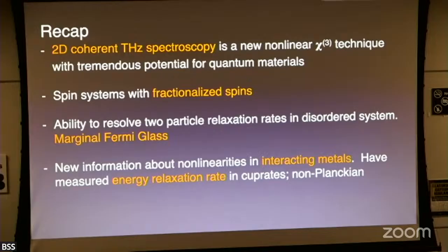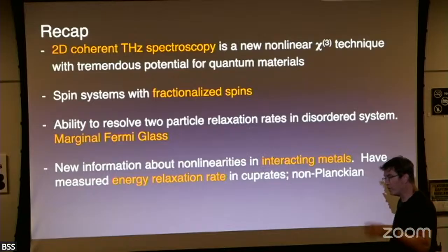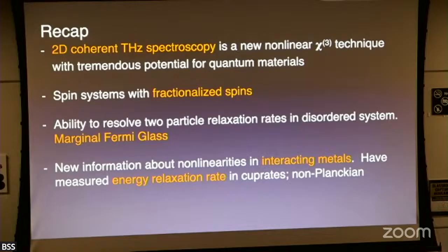So what if you go with the fluctuating? Yeah, that's an interesting question. We have an unpublished paper, not because anybody didn't like it, we just didn't get back to it. It's on the archive, on very disordered films of niobium nitride. You work in a regime where kFl is, it's dirty limit, as we discussed today. It's 10 or something. So this is not a clean metal, but it's also not something where kFl is close to 1. And the nonlinearities just die like an order parameter.